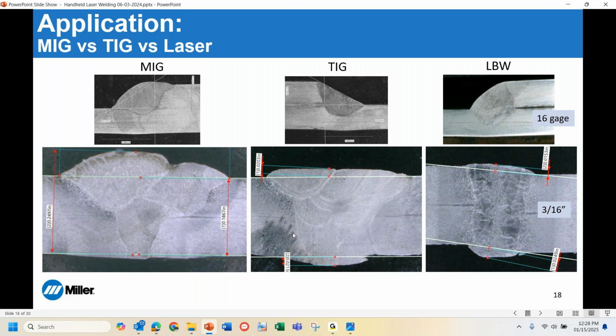And then the bottom members that you see there, again, the same thing, MIG, TIG, and the laser processes. With the MIG welding and the TIG welding process, we're essentially required to bevel the components in order to get that same weldment stacked in there, whereas with the laser welding process, we can easily accomplish that with the amount of penetration that we get into the component, and significantly reduce the prep time, the weld time, as well as the heat put into the part.